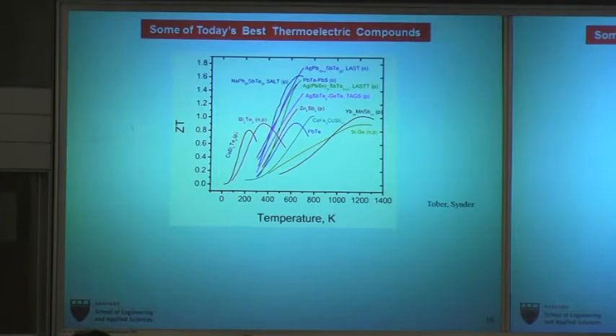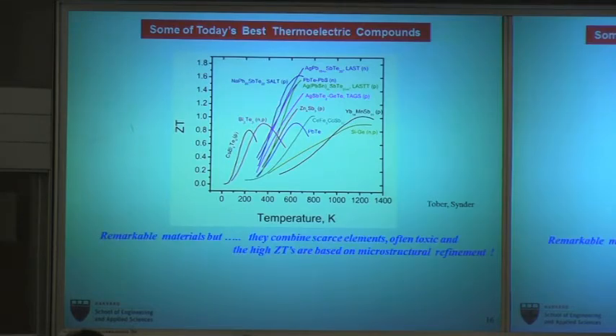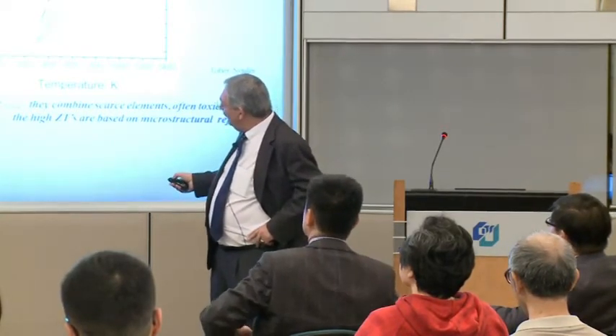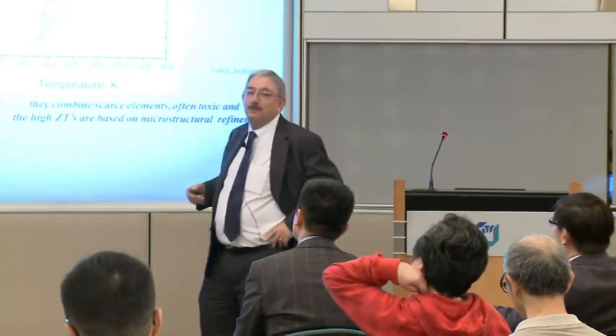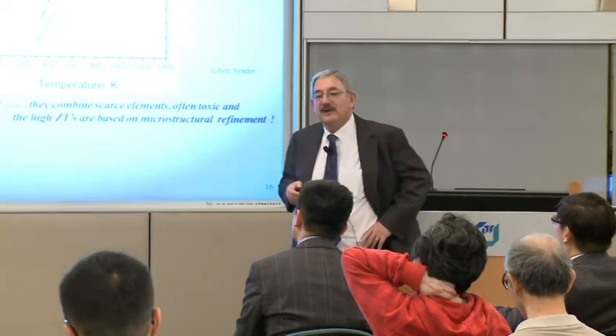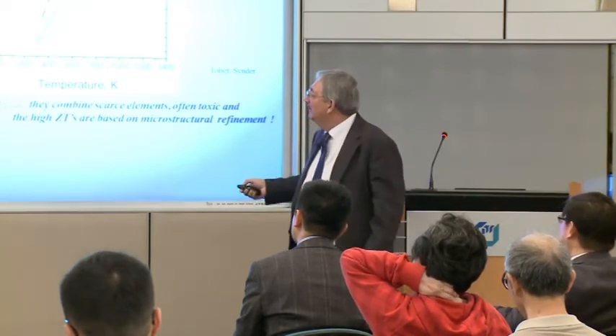The other thing to note about these is that these materials, the ones that you could use that I'll call the old materials, contain bismuth, tellurium, selenium, a number of other chalcogenides. And furthermore, many of these elements, if you go further up, can be quite rare, like ytterbium, antimony, are really rather rare.